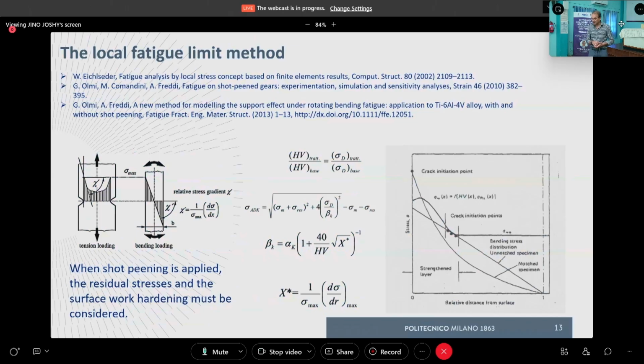What can we see here? We see the linear trend, this one, the straight line, that represents the stress due to bending in a smooth part without a notch. Okay? Then what is represented here? This line that starts from the horizontal coordinate is the depth. On the ordinate we have the stress. This line represents the so-called local fatigue limit that is calculated by means of this other formula.